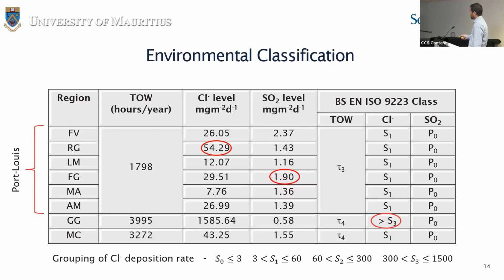It is observed here that for chloride deposition rate, all sites are of the S1 category, except GG, which is a southern marine site, having a chloride deposition rate higher than the upper limit of the highest category, which confirms that this is a chloride-rich atmosphere. All the sites in Port Louis are the S1 category.